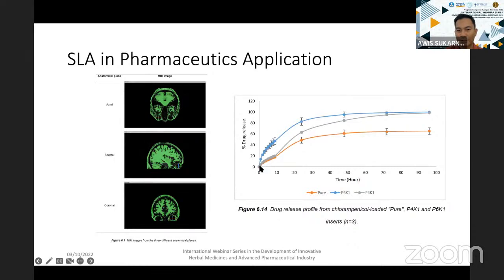This is because at this point it starts to dissolve slowly, but between the 10 hour and 24 hour marks, the tablets start to crumble and break into smaller pieces. That's why at this point the release profile is quite fast, because the tablet just crumbles and breaks into smaller pieces. Compared to this one, which just dissolves slowly without breaking the tablet.